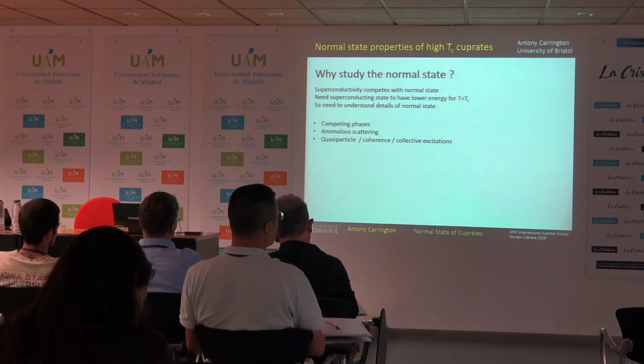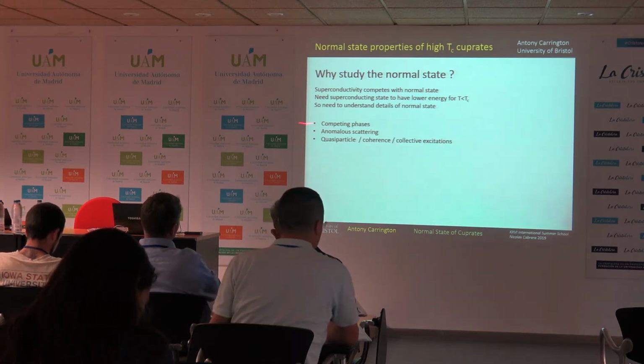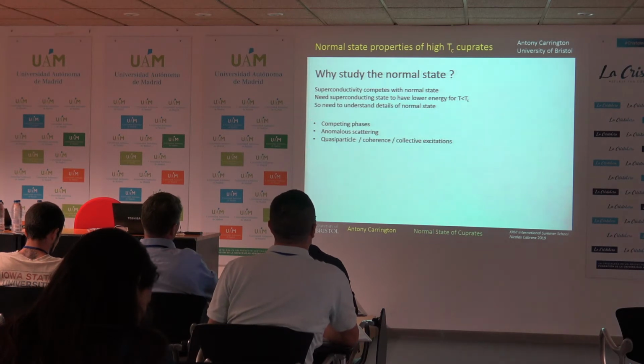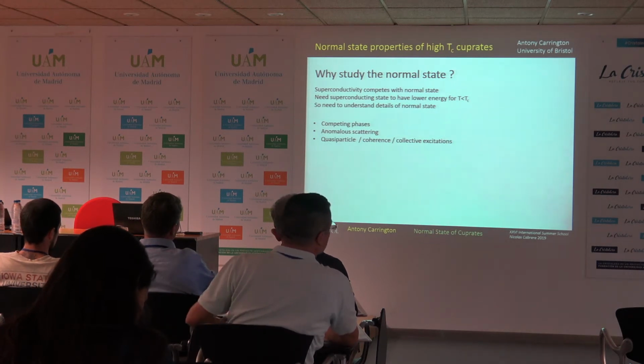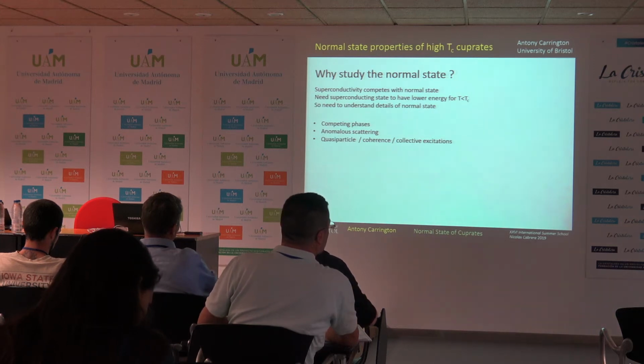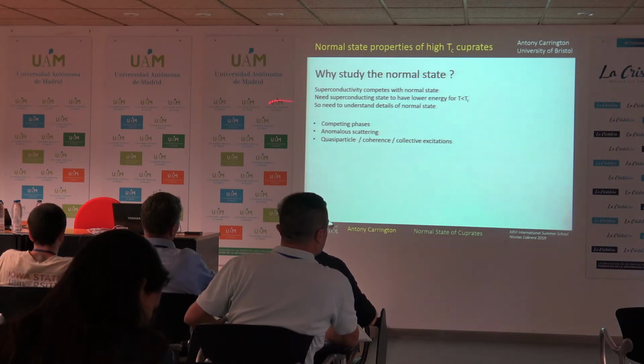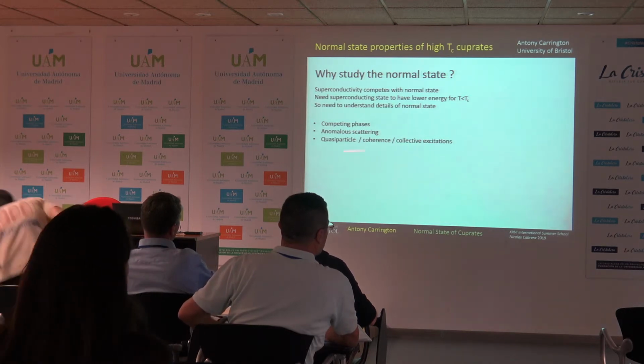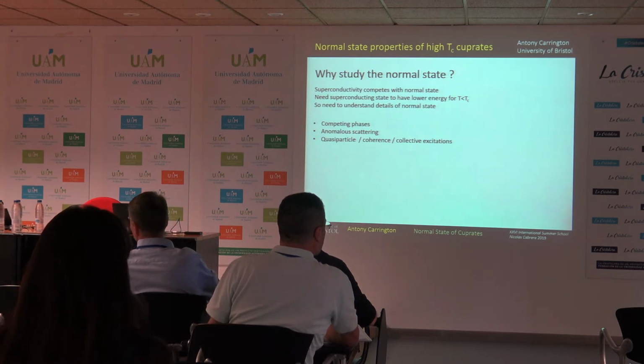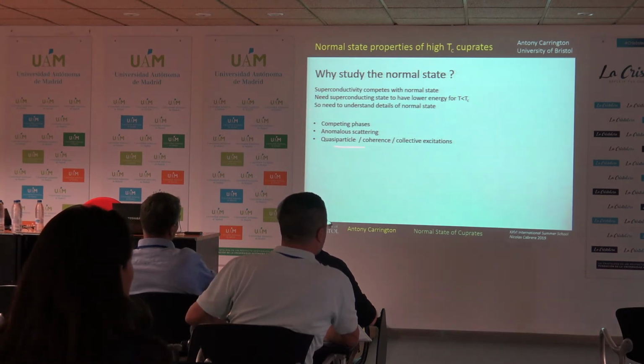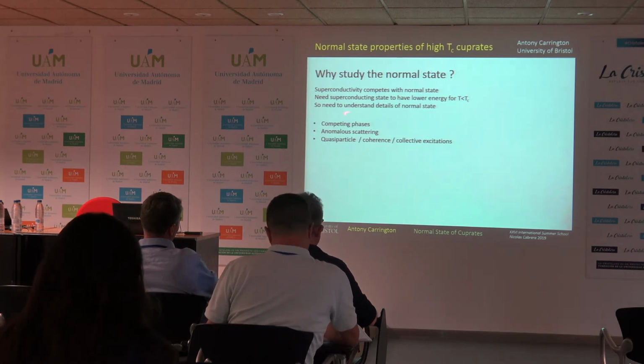But actually, by looking at the normal state, you can identify things like what are competing phases. So there are different possible ground states. They're not just normal paramagnetic metal ground states, but they can be other things like charge density waves, spin density waves, or things much more exotic. So what are those competing phases? What are the scattering processes that are involved? So the things which are causing pairing are also scattering in the normal state. So we want to try and identify what those are.